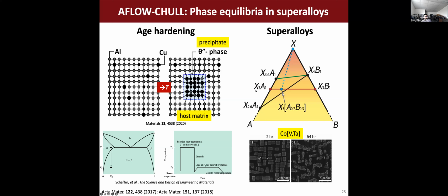Okay, so let's say we have a range of compositions over which this precipitate can exist. If we want the system to be in thermodynamic equilibrium with the host matrix, we can have a boundary which crosses here on this side. So we need some piece of this tie line which can access this top point. If I have a tie line which crosses this boundary like this, I still have a range of compositions where there could be a tie line that connects the composition of interest and the host matrix, the pure aluminum.